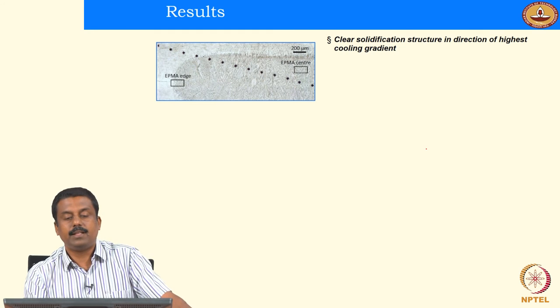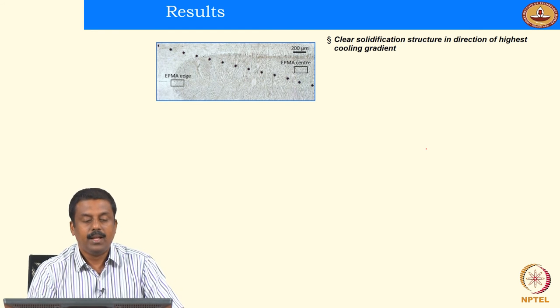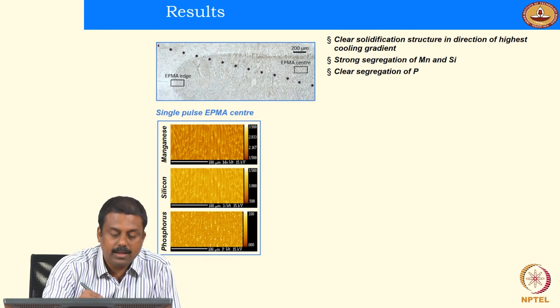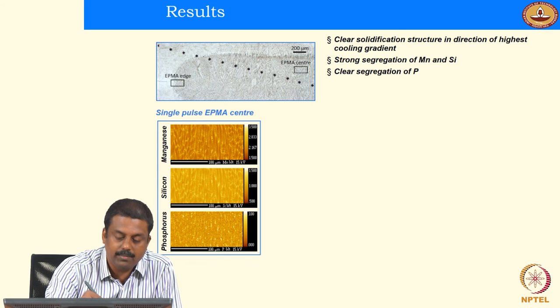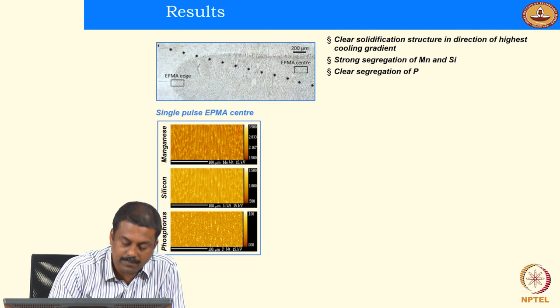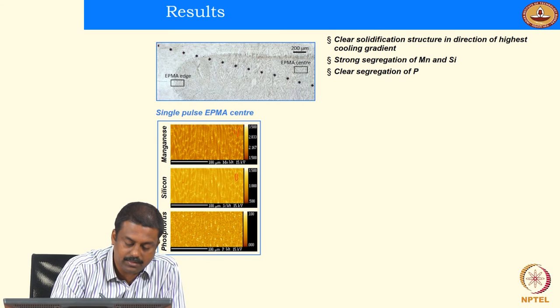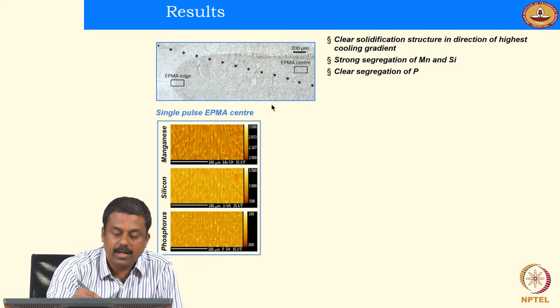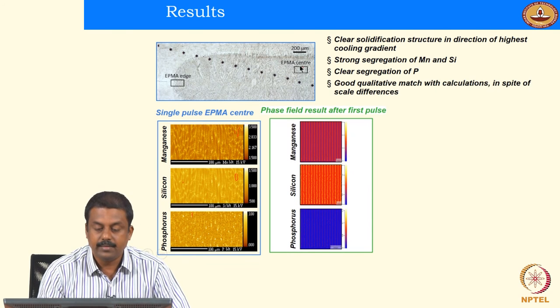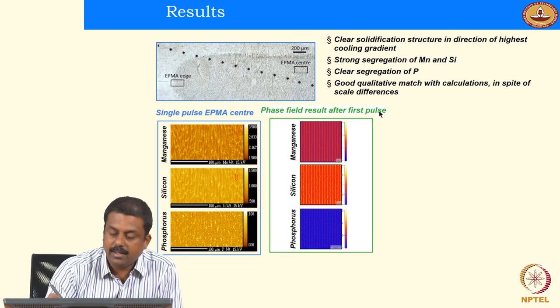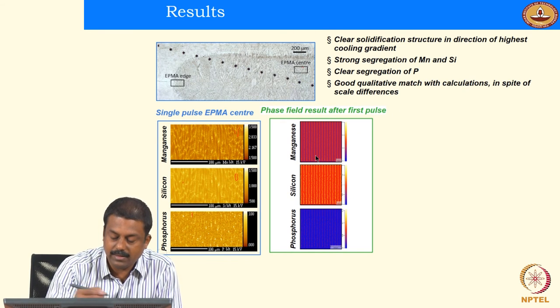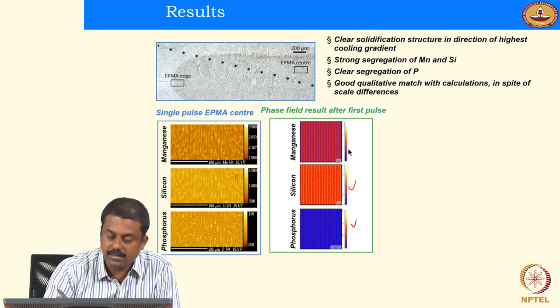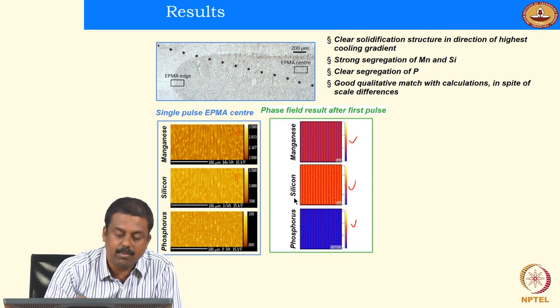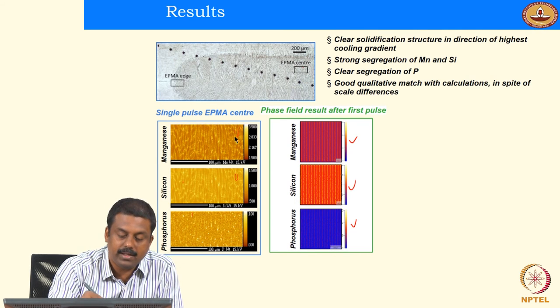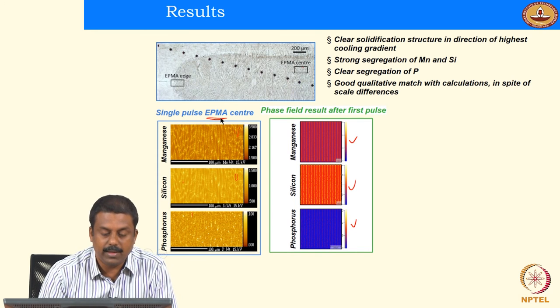So what is the result? Actually, we are seeing that in the single pulsing, in the experimental result also, we see segregation of phosphorus, silicon and manganese at the dendritic boundaries. You see here in this picture, at the dendritic boundaries the manganese is enriching the boundaries, silicon is enriching, as well as phosphorus is also enriching, at the solidification boundaries at the center as well as the edge. And you see the calculation results I showed in the previous slide also. You see the clear segregation of phosphorus, manganese and silicon at the dendritic boundaries, which is clearly seen also in the experiment by the elemental mapping, electron probe microanalysis mapping.